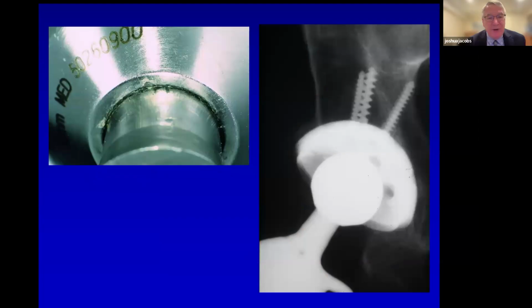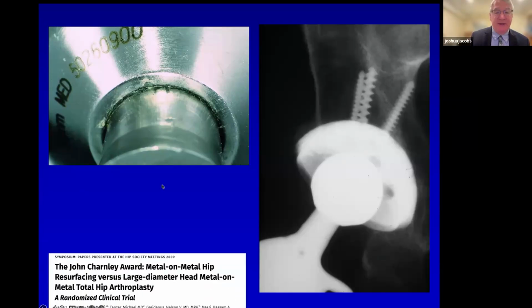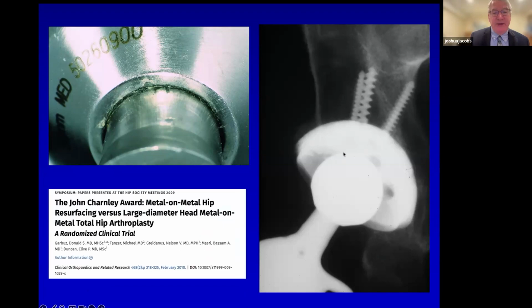We've learned a lot about the potential bioreactivity of corrosion debris. This is another situation that's not a metal-on-metal bearing per se. It's a metal-on-metal contact area. It's a modular junction of a cobalt alloy on a cobalt alloy femoral component. This is the head on the neck. And if there's any micromotion there or fretting between the head and the neck, it can generate this debris that we see here, resulting in this massive osteolytic lesion in the periacetabular region of the pelvis. You can see that hole in the bone.